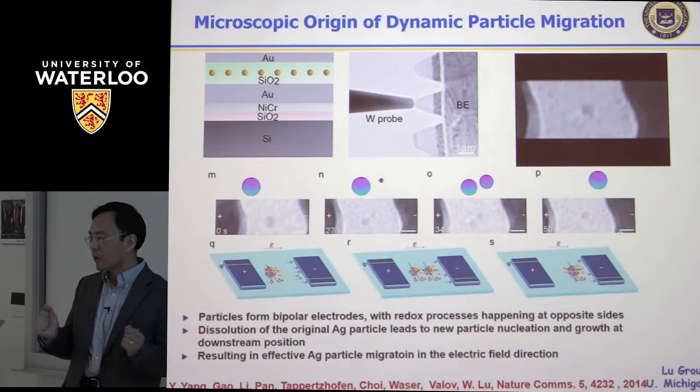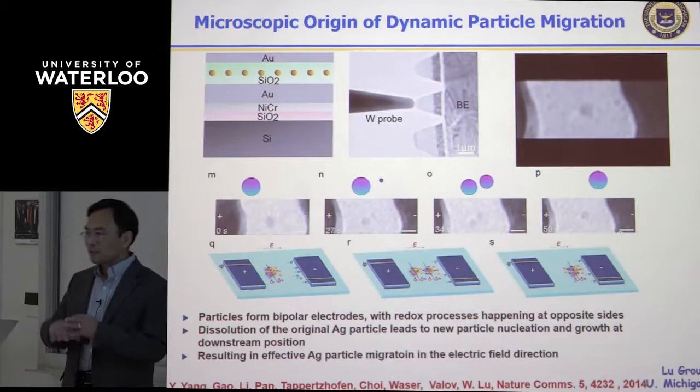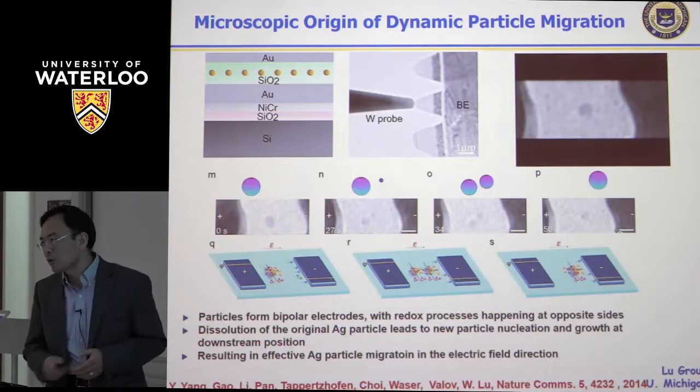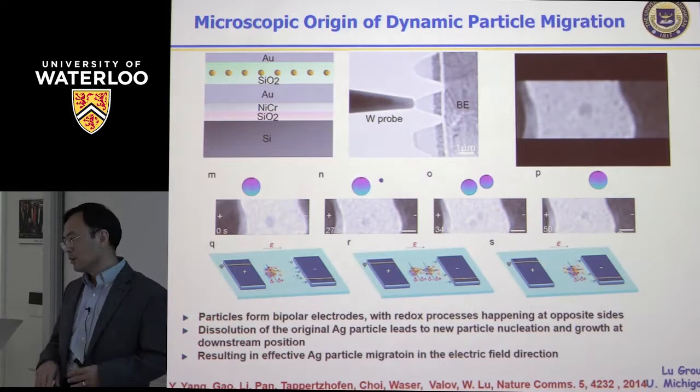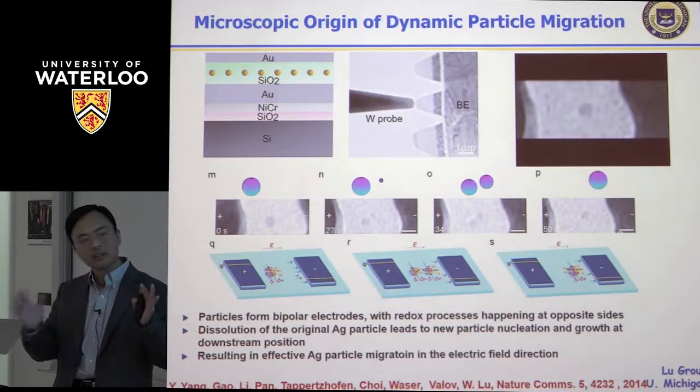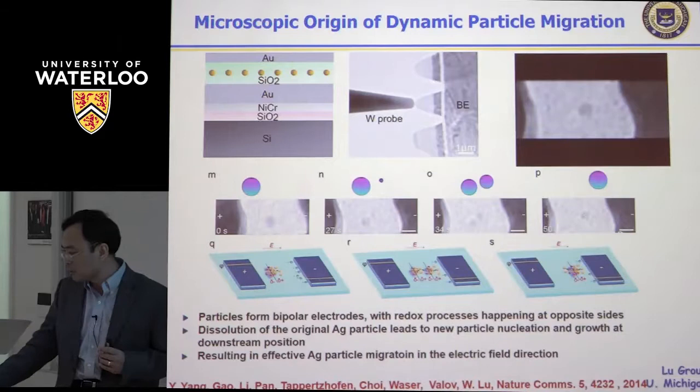People have talked about building electronics based on single atoms, right? People use scanning tunneling microscopes at very low temperature to move atoms one by one. Here we are also moving atoms individually, and controlling the electrical property individually, but we do it at room temperature and inside a circuit. You can control the film property and the device resistance in situ using this approach. And because we are not providing a lot of current through the device, this is completely field driven, so you can do it in a very well controlled fashion. You are only moving atoms individually, so you can cycle the device many times, okay?